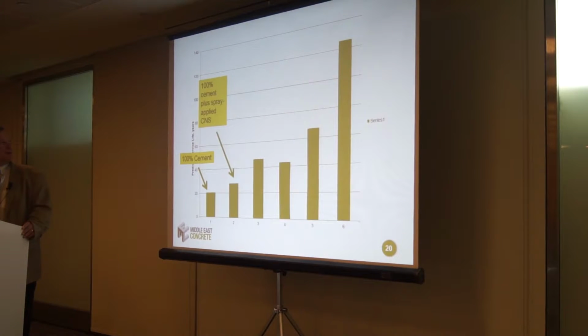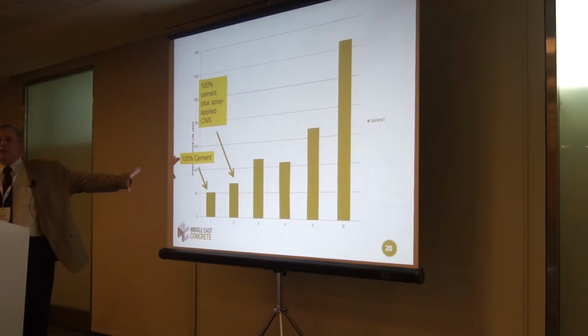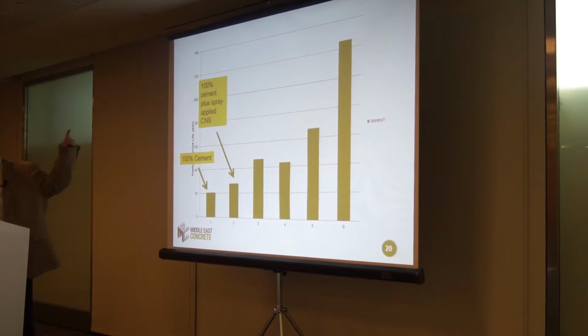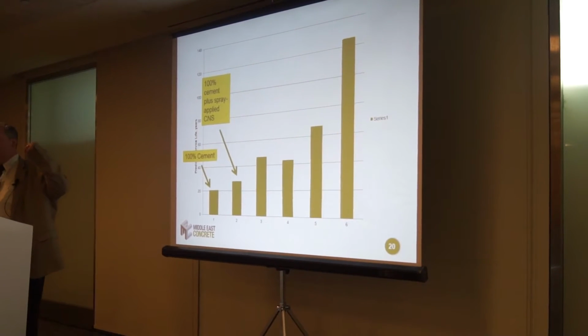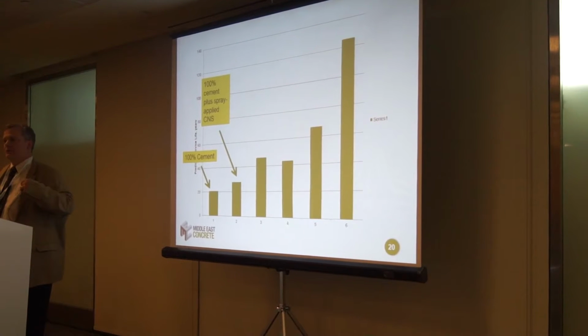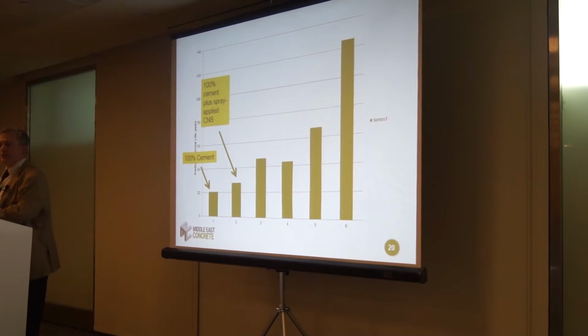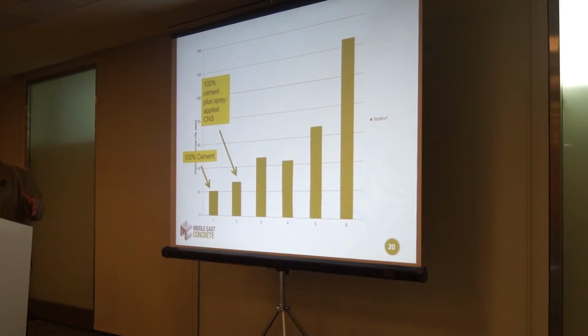So the next thing that we did is we applied a spray-applied colloidal nanosilica to this 100% cement concrete with no pozzolans, and we were able to extend the lifespan up to close to 30 years. So we gained 10 years, or roughly a third, by applying colloidal nanosilica. We used the chloride diffusion coefficients that I showed you earlier from the ponding test that we had run.